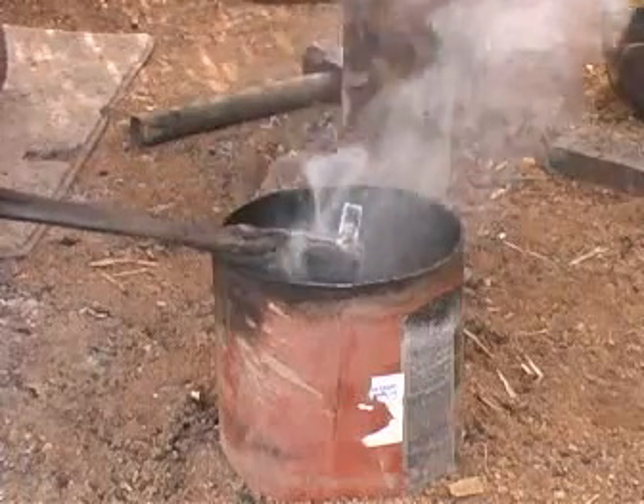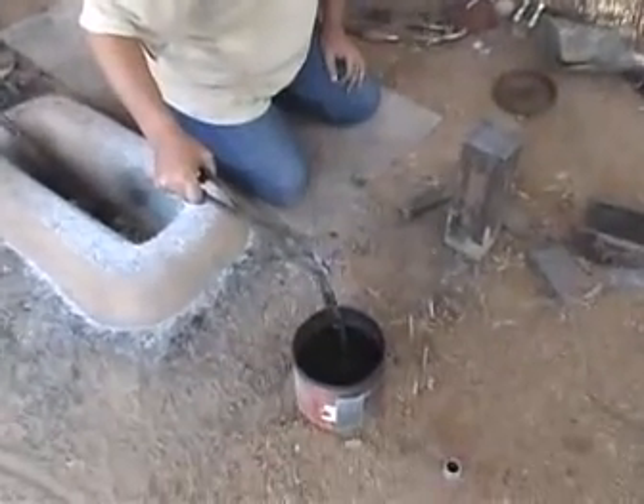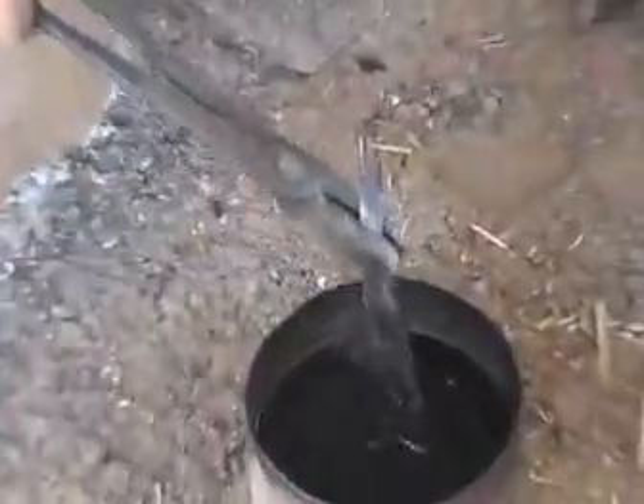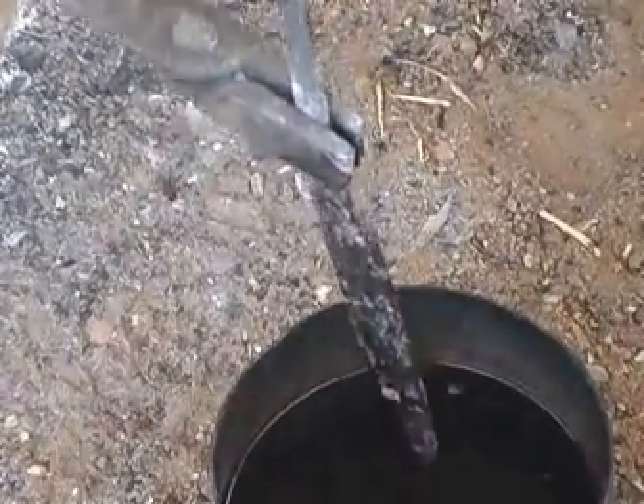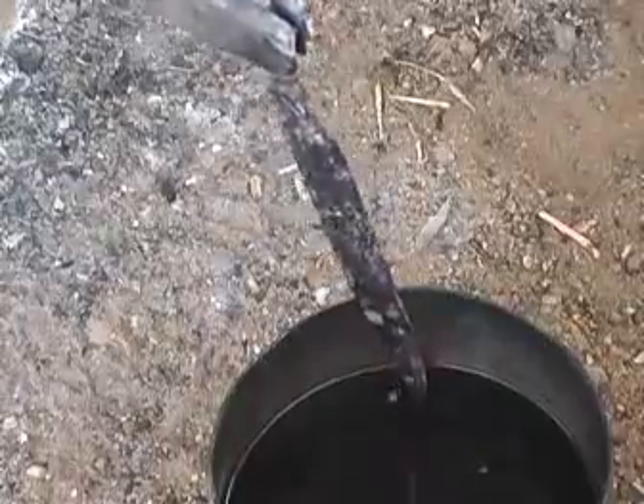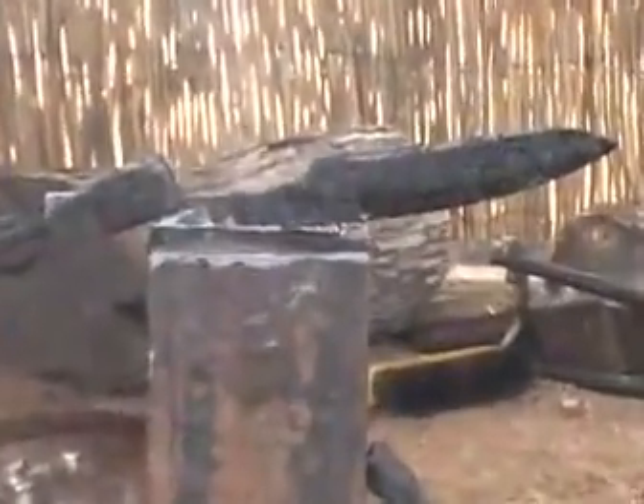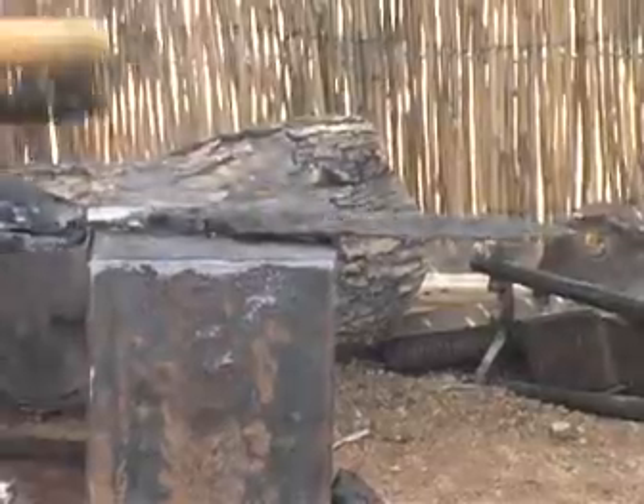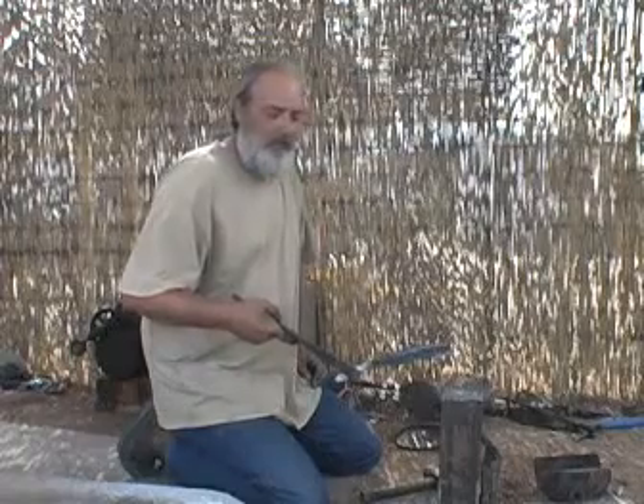Now it should be fully hardened. I'll check this with a file along the edge to see if the file skates across the edge. And that'll tell me if it's gotten fully hardened or if there are any soft spots. Okay. Looks straight, didn't warp. So now I'll just let it cool to air temperature, and it'll be ready to be tempered.